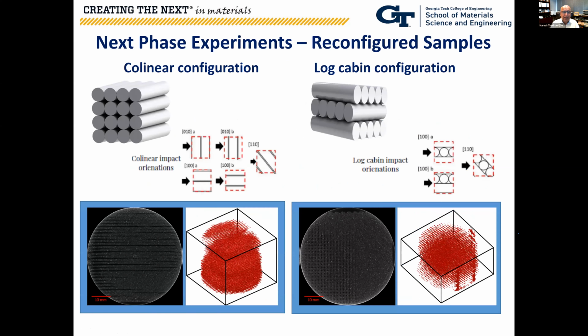Now, the fact that we did not see much of a difference or an effect of the orientation, we have done another series of experiments on samples with a greater amount of porosity as well as control porosity. So a new set of samples was fabricated with collinear configuration as well as log cabin configuration. We've performed these experiments last fall, and these are still currently being analyzed. So I will have to get another opportunity to present the results of that.